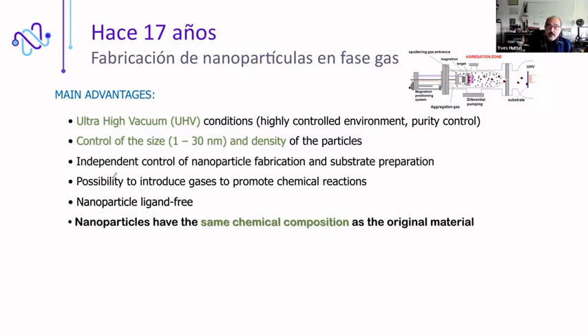We can also introduce gases inside the aggregation zone in order to promote some chemical reactions with the atoms when the nanoparticles are being formed. The nanoparticles are ligand free, which means that we can use all the surface of the nanoparticles. And the nanoparticles have the same chemical composition as the original material.